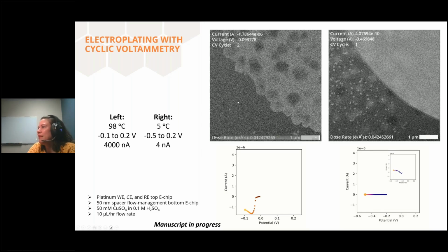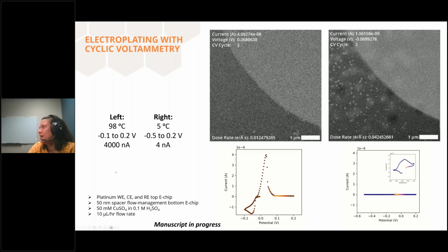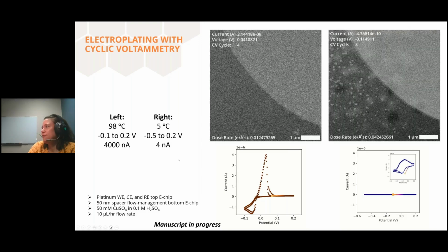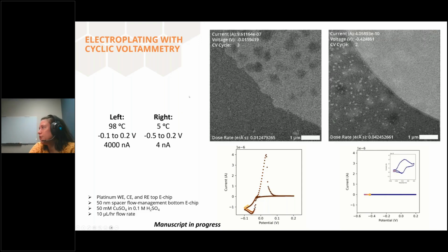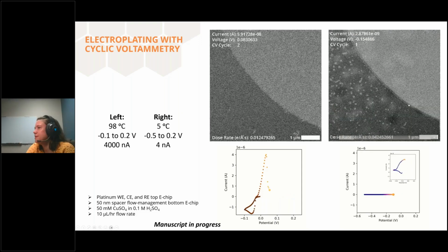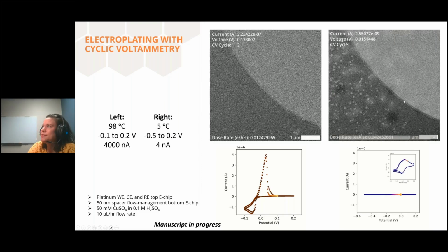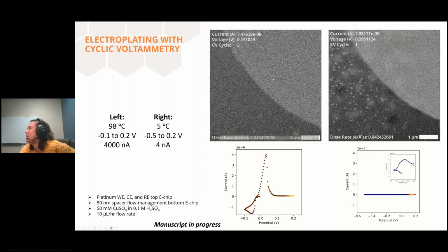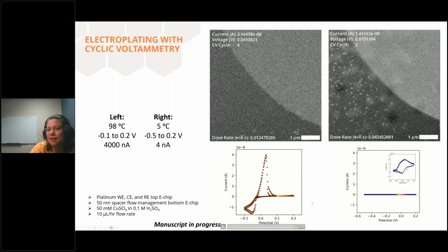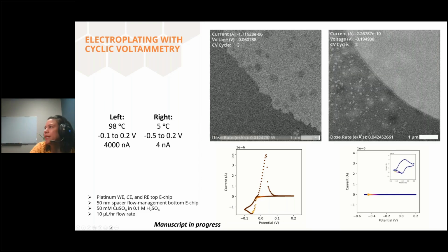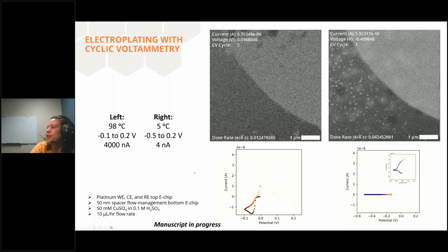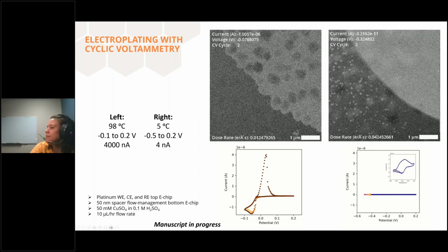And so here on the left, we've got 95 degrees. I think it's 95, maybe it's 98. 90-something degrees on the left and 5 degrees on the right. And if I hit play, there we go. You can actually see a big difference in the amount of plating, first and foremost, and the size of dendrites. Dendrites isn't quite the right word, since these don't look dendritic to me. But you can definitely see that there's a lot more plating occurring, and certainly a lot faster in the higher temperature plating experiment than on the right.